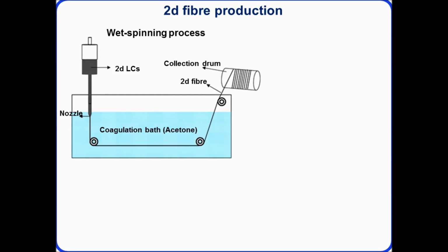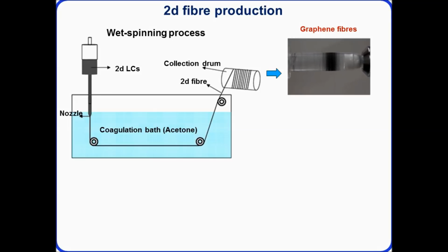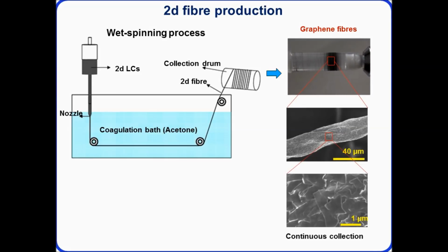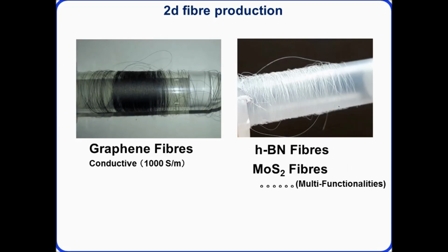So we can make two different processes. The first, we can produce fibers, so we can inject the ink as it comes out of the microfluidizer into a bath of acetone, and what that does is it precipitates the ink in a very fine structure. We can actually grab hold of it with some tweezers and start collecting it on the drum, so we're actually pulling a fiber from this bath. Here you can just see a video showing the continuous motion of this graphene fiber being collected. Okay, so if we look under a microscope, we can see they're around 40 microns in diameter, and you can see the sheets of graphene aligned nicely. So we can produce conductive fibers.